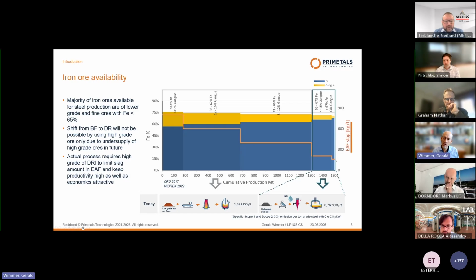And we see the very good iron ores here on the right with very small gangue result in reasonably low slag amount in electric arc furnace, so the electric arc furnace can handle. Nobody's happy about too much slag because slag in electric arc furnace is reducing the yield, it costs energy, but as long as this amount is low, we can live with and we can use it. These low-grade iron ores and these medium-grade iron ores would result in very high slag amounts, 600 kilograms per ton. So the slag pot on such a furnace would be bigger than the steel ladle. And that's why these medium to low grade iron ores today are used in a blast furnace and they do not fit to the electric arc furnace.